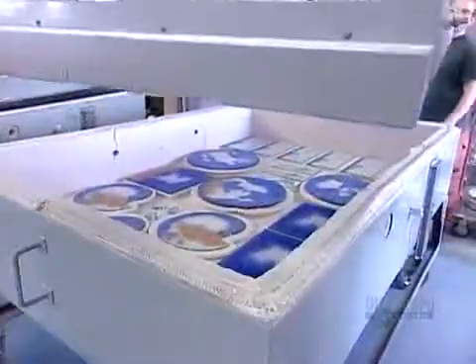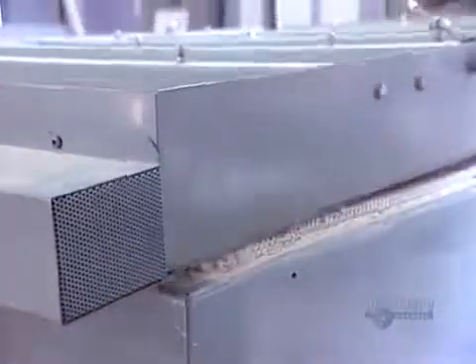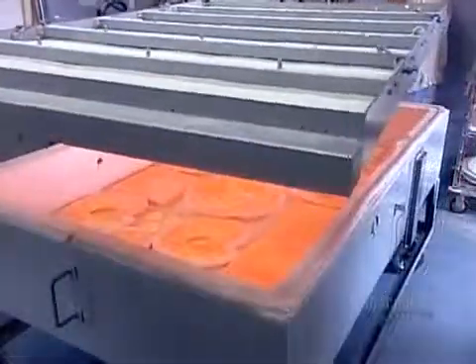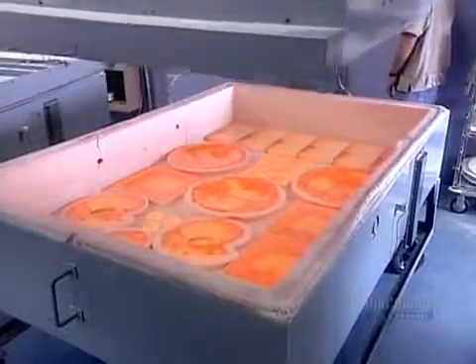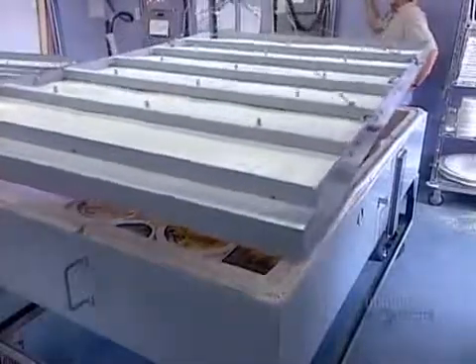These small pieces of glass will become the paint pots on this glass replica of an artist's palette. It takes an hour and a half for the kiln temperature to climb to a scorching 843 degrees Celsius. At peak temperature, they open up briefly to make sure everything is progressing well. The glass should be the consistency of maple taffy and glowing bright red — if it is, they can close the kiln and begin the cooling phase.